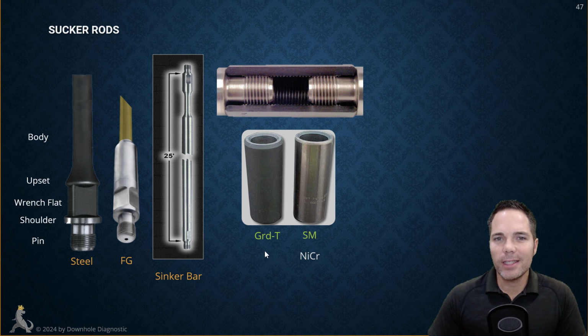So there are two different couplings as specified by API. We have a grade T coupling. This is a softer type of metal. And then we have a spray metal coupling. And a spray metal coupling is a grade T coupling, except they shave off a little bit of the exterior and they put on a very hard surface finish that is going to be nickel chromium. And this hard surface finish here is good for corrosion. It's also good for preventing wear on the coupling, but when you have a very hard surface finish here, it might prematurely wear your tubing down because this surface is harder. So if you have rod-on tubing wear with spray metal couplings, it might prematurely wear your tubing down as opposed to wearing the coupling down.